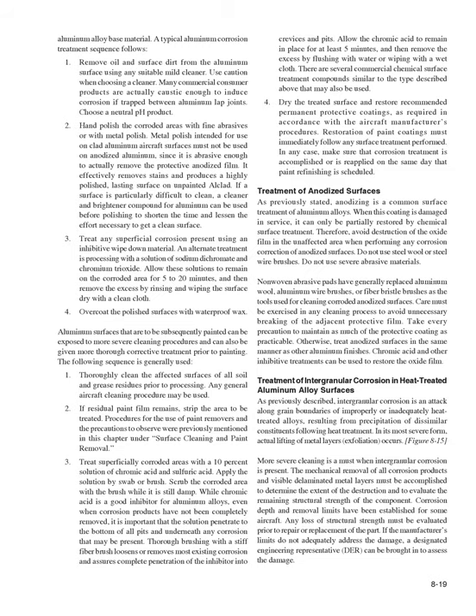Metal polish intended for use on clad aluminum aircraft surfaces must not be used on anodized aluminum, since it is abrasive enough to actually remove the protective anodized film. It effectively removes stains and produces a highly polished, lasting surface on unpainted alclad. If a surface is particularly difficult to clean, a cleaner and brightener compound for aluminum can be used before polishing to shorten the time and lessen the effort necessary to get a clean surface.